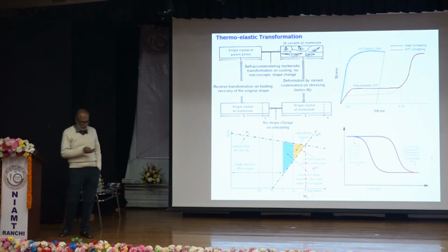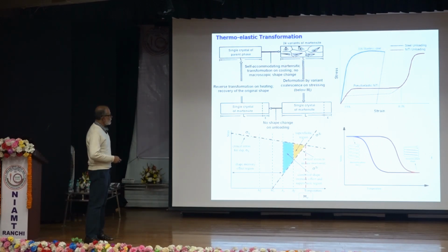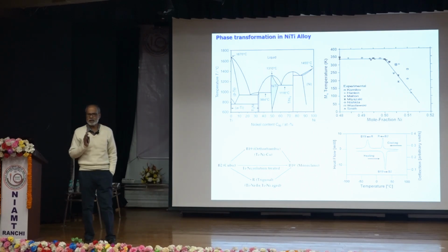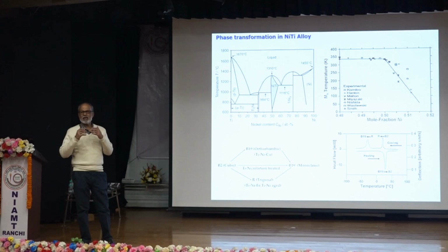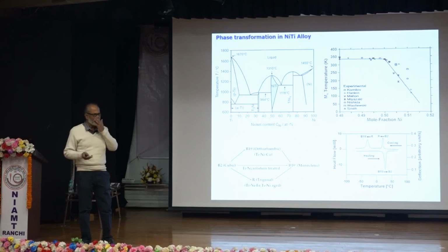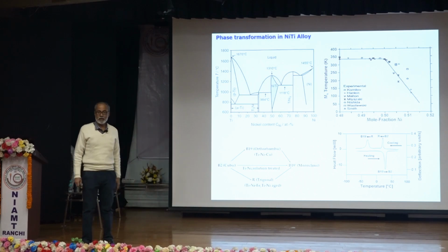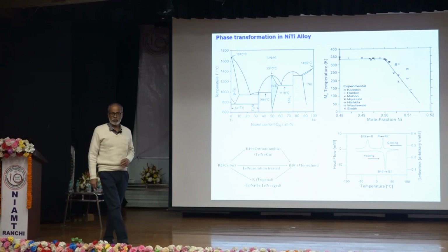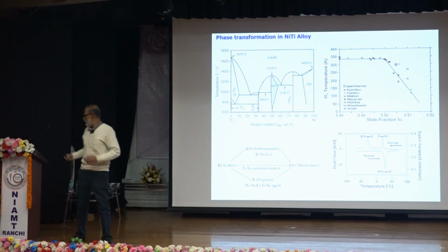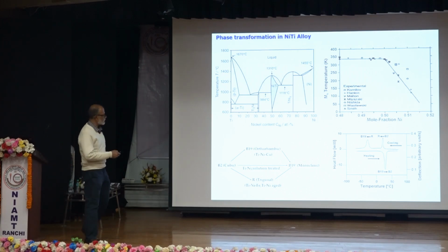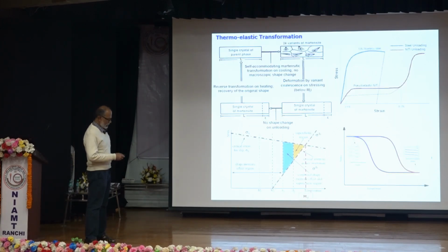Now we can see the whole thing is very coordinated, very systematic, right? So it calls for a very organized microstructure. If there is extreme randomness, extreme misorientation, a large amount of defects, you don't get what you want. But at the same time, nickel titanium itself is not very strong. Our intention, this was the basis of our work, we thought if we can strengthen this alloy by a certain hardening mechanism, two common hardening mechanisms being either cold deformation or precipitation in metallurgy.